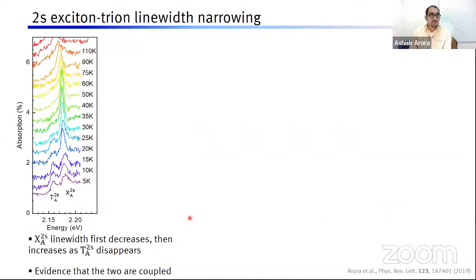Now, one further piece of evidence is the following, and it's very nice: when you have a trion state appearing below an exciton state, then an exciton can scatter back to this trion state by capturing an extra electron. Therefore, the line width of this exciton is rather large because there is a scattering contribution from one state to the other. However, if this trion state vanishes for some reason, then this scattering channel won't be available. So in that case, the line width should become smaller because there is less scattering of this exciton state to some other states.